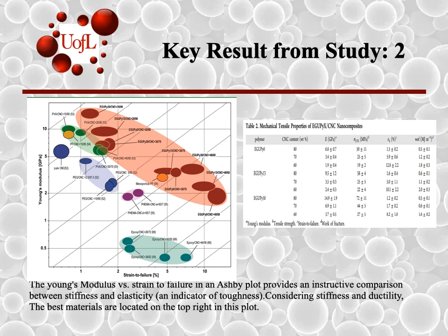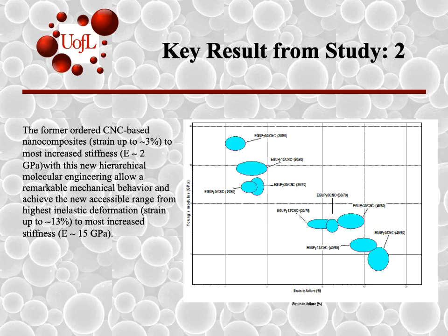Another key result from the study: based on the literature values, the authors plot the Young's modulus versus strain to failure in an Ashby plot to provide an instructive comparison between stiffness and ductility, which is an indicator for toughness. The best materials combining stiffness and ductility are located on the top right in this plot. The authors showed that the former order CNC-based materials, with stiffness up to 2 gigapascal and a strain up to 3%, can allow a remarkable behavior and achieve the new accessible range from highest inelastic deformations, which is up to 13%, to the most increased stiffness, which is reaching up to 15 gigapascal.